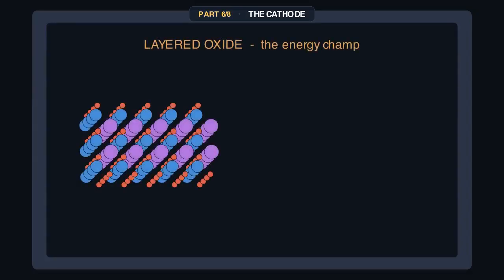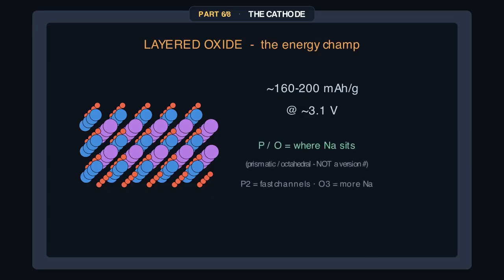Branch 1, layered oxides, the energy champs, the closest thing to a lithium cathode. Sodium sits between sheets of metal oxide, and you'll see a notation, P2 and O3. It is not a version number. The letter is where sodium sits, prismatic or octahedral, and the digit is how many oxide layers repeat. P2 has wide channels, so sodium moves fast. O3 packs in more sodium, higher capacity, but slower. They reach roughly 160 to 200 mAh per gram, near 3.1 volts. The catch, honestly, they're moisture-sensitive. Humid air pulls the sodium out and grows a crust, so they're handled dry, and which of the 2 ages worse is genuinely still argued.